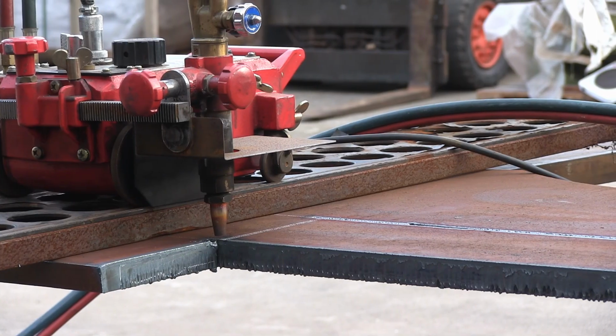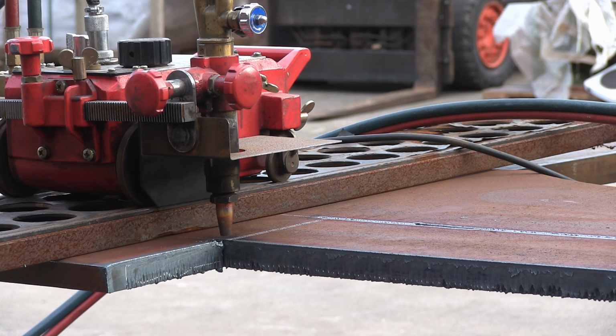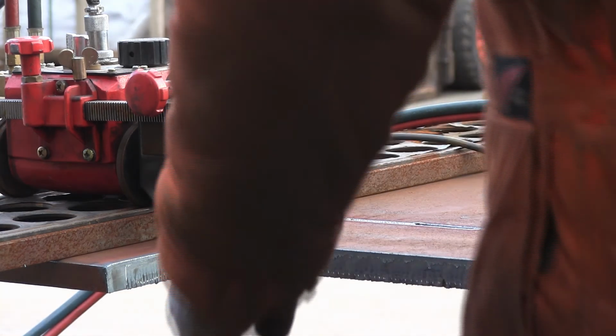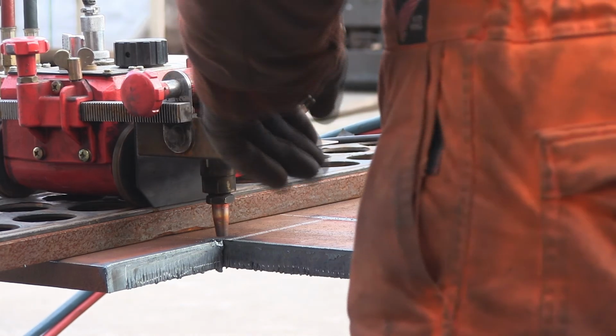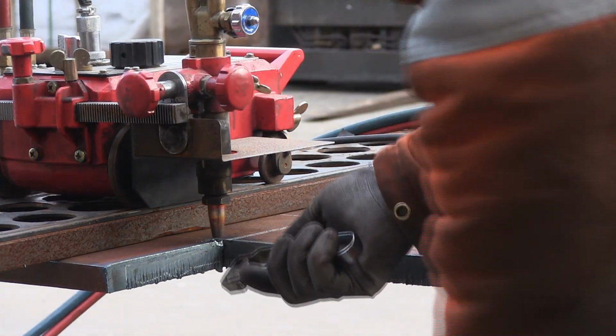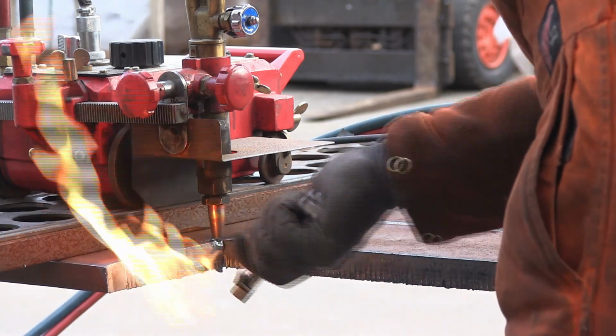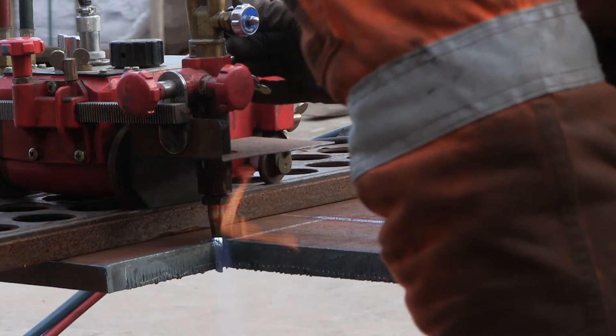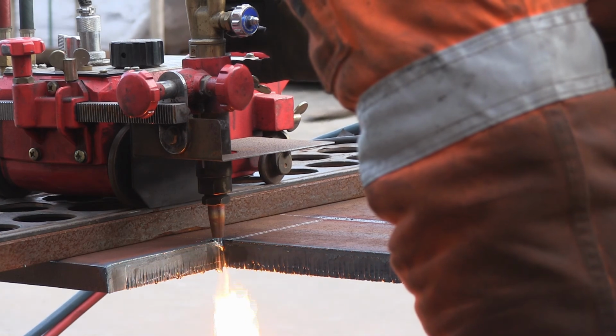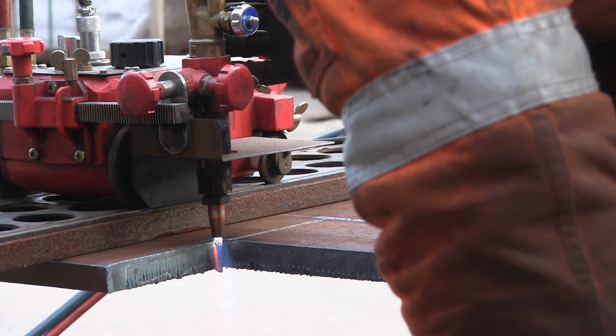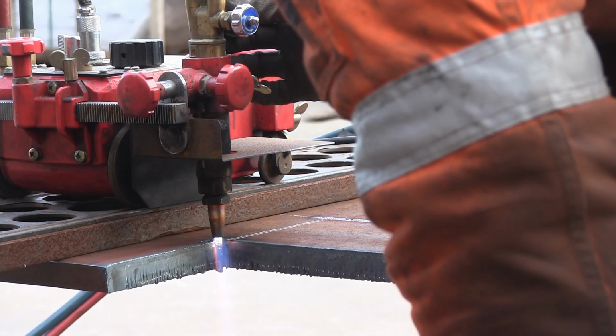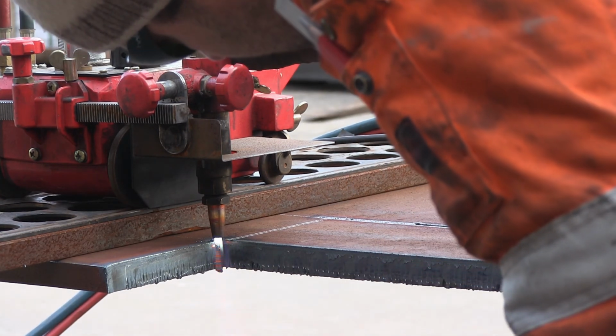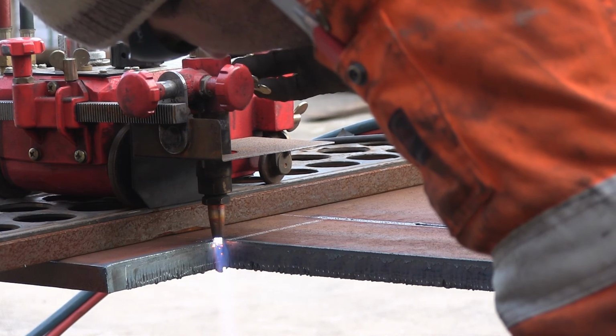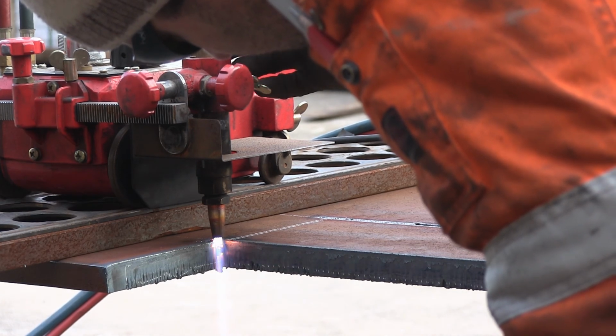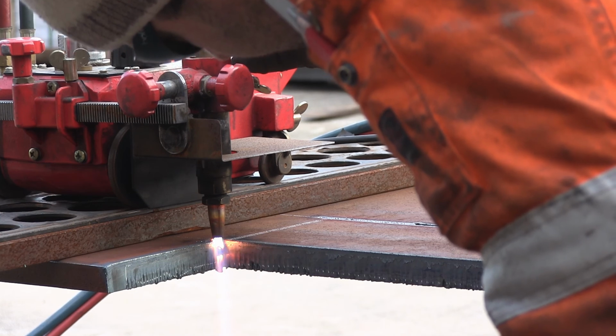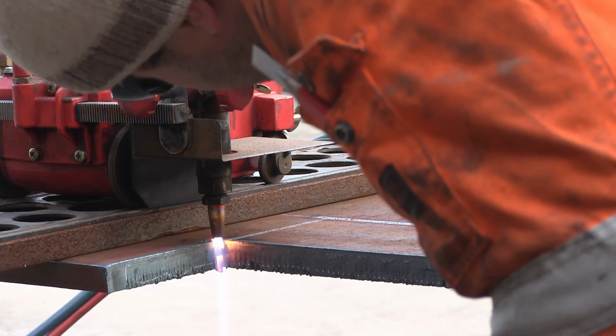Sometimes when you cut relatively thin steel like this, 25 mil or thinner, due to the travel speed and the heat, there isn't that much material being removed during the cut. So you may not end up with such a strong fountain as you've seen when I was cutting 50 mil steel. But you will see a very steady stream of steel coming out from the plate, and it also will carve forward in the line of cut, so it will carve in the same direction as you are cutting.